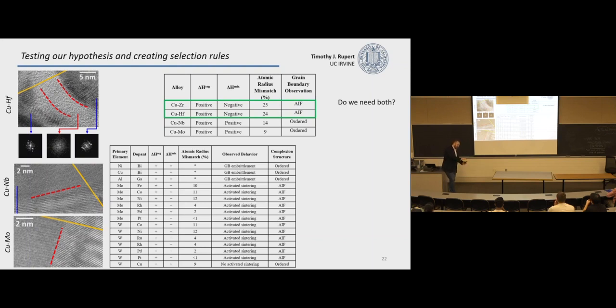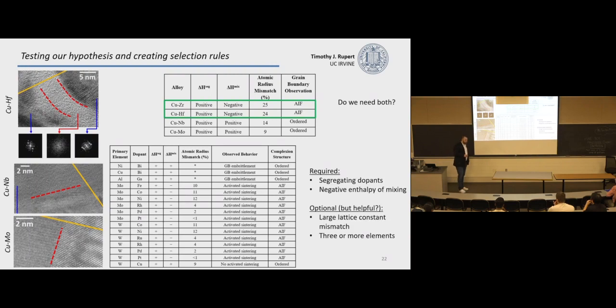So when I showed the density versus temperature curves, that big jump in density of a consolidated sample is related to these amorphous intergranular films. So we could go and look at a bunch of data in the literature and, for example, find that in some of these tungsten alloys, there's materials which have a negative enthalpy of mixing, but only a small atomic size mismatch. So we're able to sort of go through and refine our understanding.